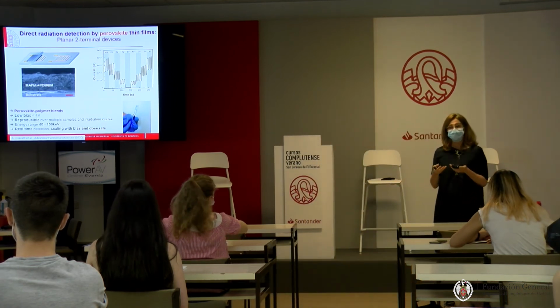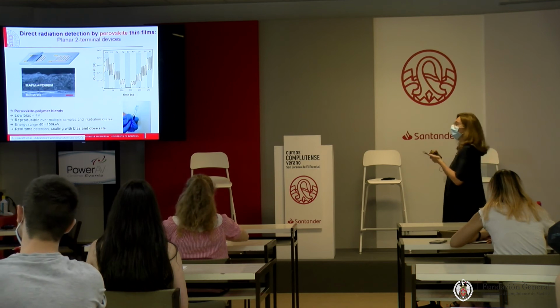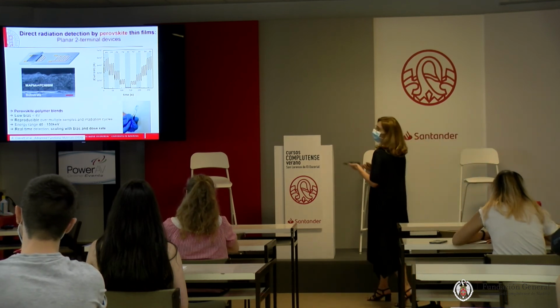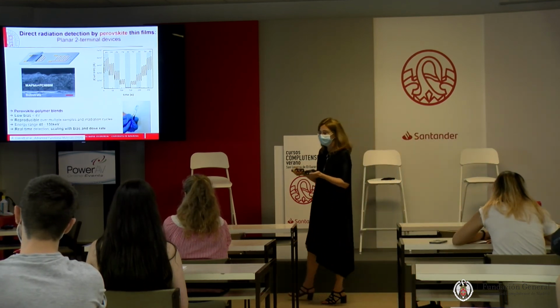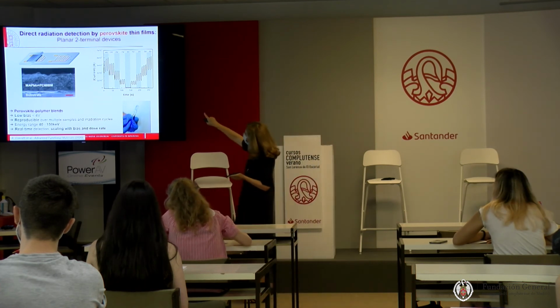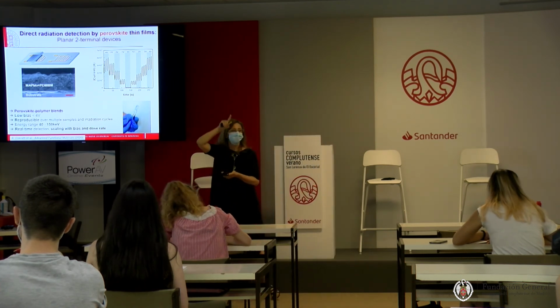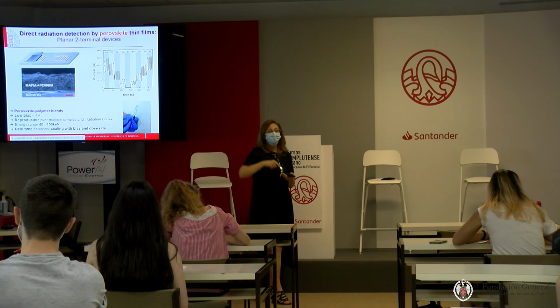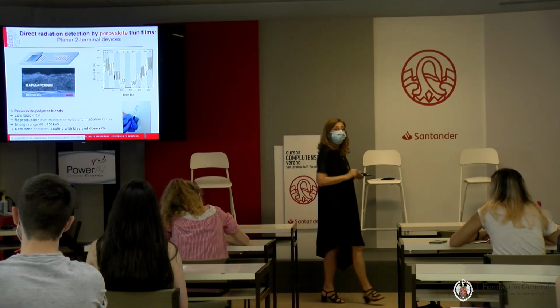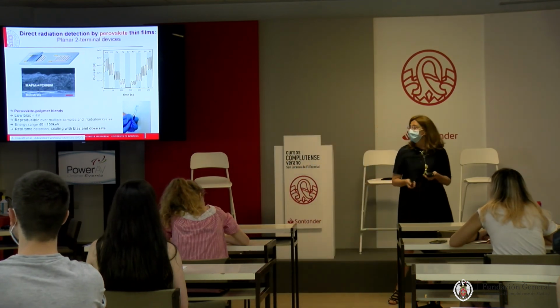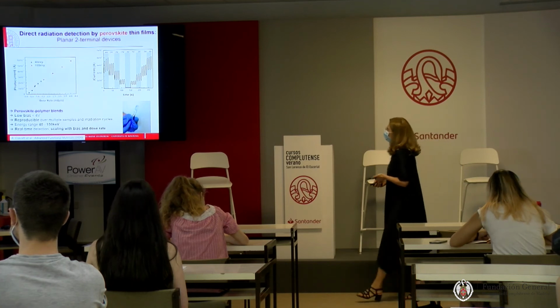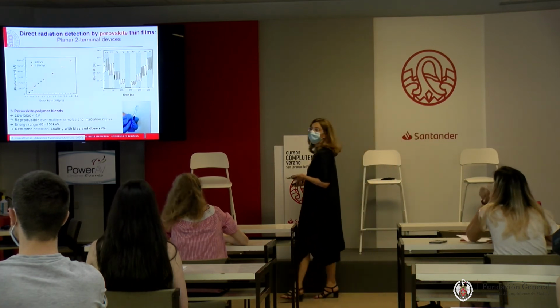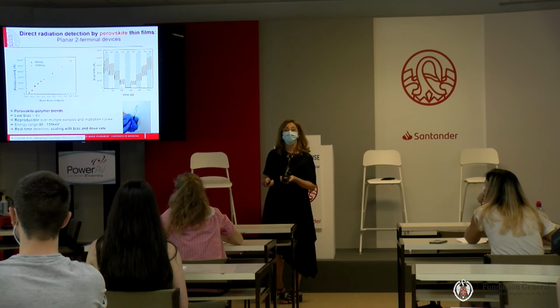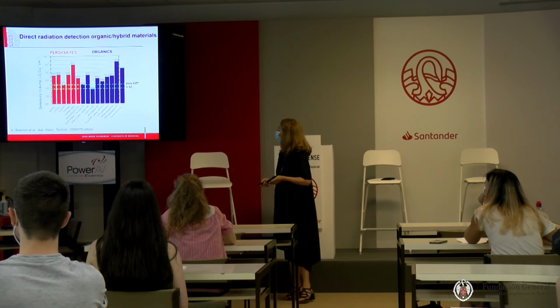It's a polycrystalline film that has very good transport properties, good enough to grant you a nice photocurrent to an on-off X-ray beam at very low operating biases. And the sensitivity is also very good at high energies, up to 150 kilo electron volts.